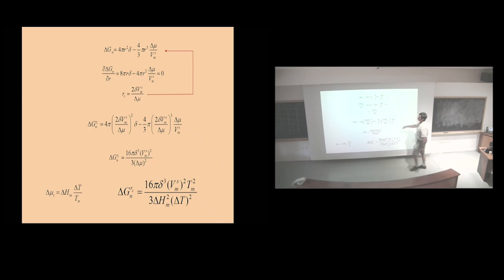Now, all I did here is just put in the area of a sphere and the volume of a sphere. The equation's the same. You differentiate, set equal to 0: maximum, minimum, point of inflection. Remember that? And then you solve for RC. Then you put it back in there, and it gets really funky. And at the end of it, you end up with an expression that looks like this. It's just arithmetic, and your free energy now has a whole bunch of terms, which involve the interfacial tension, the density, the temperature of melting that Adam's going to give us, the enthalpy of melting, and the delta T for crystallization in the class. So all of them are numbers that you can get.